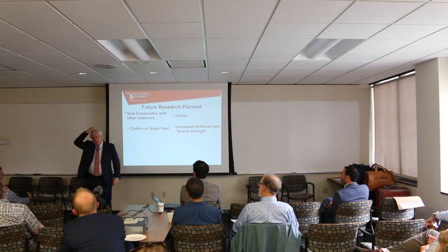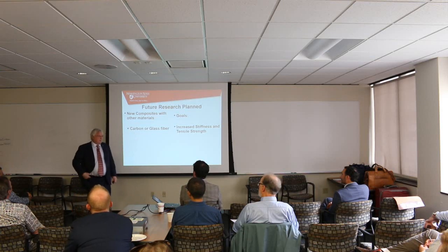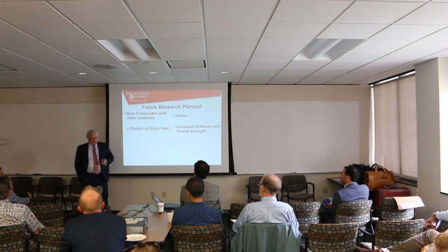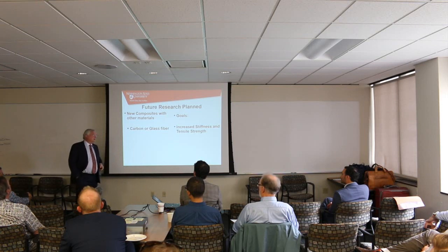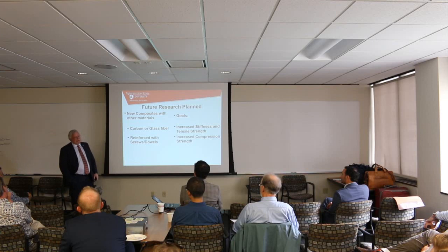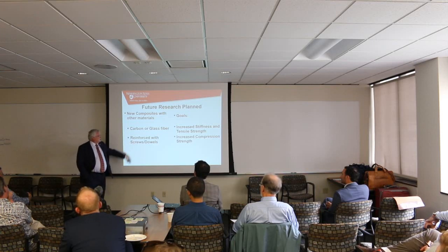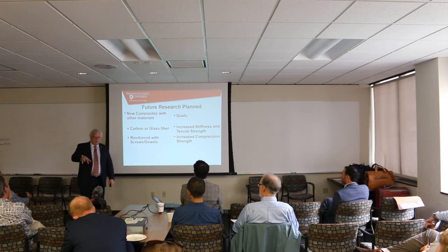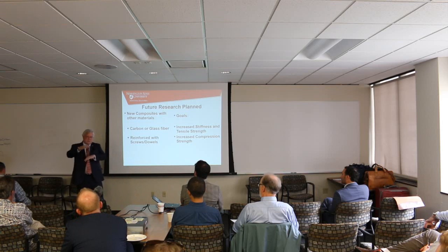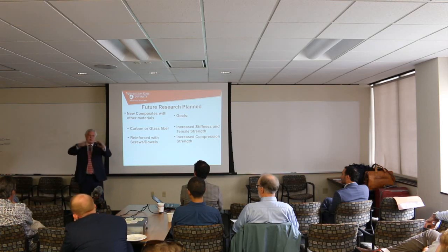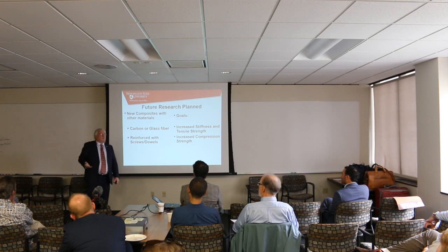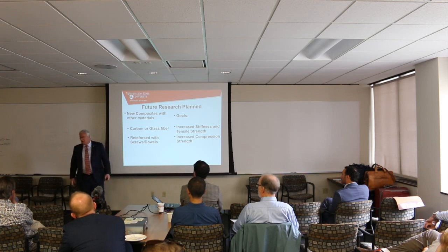But that's what I've done a lot of for our light frame. And so MKA is trying to come up with a way they can look at increasing the stiffness and the tensile strength, as well as improving the vibration response of those floors with concrete toppings, composite action to the CLT. Or, and theirs is nail laminated. We're reinforcing the compression strength by strategically putting screws perpendicular to grain so that you improve the compression, similar to how you reinforce arches and glulams for tension perpendicular. We're doing it for the compression to try and improve the bearing for platform construction and maybe make that function a little better.